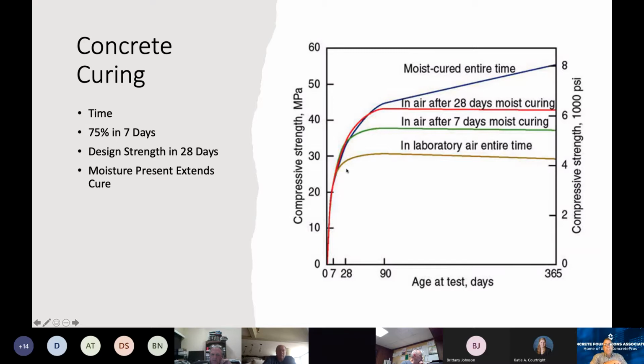It's going to level off, and then because it's in laboratory air, which has a relatively low relative humidity, it's going to actually be pulling moisture out of the concrete cylinder or out of the concrete curing, which is then going to slow its opportunity to gain, and it'll level off, and after about 90 days, it will no longer gain any strength. It doesn't have any more water available to it. If we keep it in moist curing environment for 7 days, instead of just putting it in the air, you can see that the 28-day strength is greatly enhanced and will go almost another 1,500 psi on this particular curve in the 28-day strength, just because we give it moisture early on in its age.